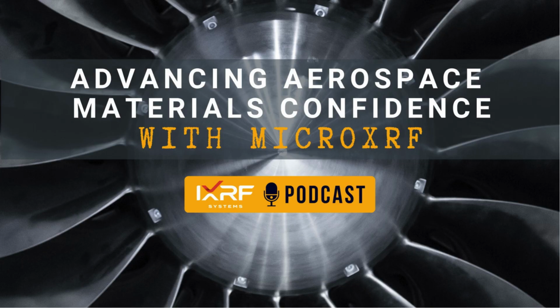You're altering it. If you wanted to test a thermal barrier coating, you'd have to literally slice off a tiny cross-section to see how the elements diffused. You're sacrificing a piece of a very high-value part. Okay, so how does MicroXRF change that equation? Well, the key capability here is getting spot sizes down to a really remarkable 5 to 10 micrometers. That's on par with the size of a single large grain in an alloy.